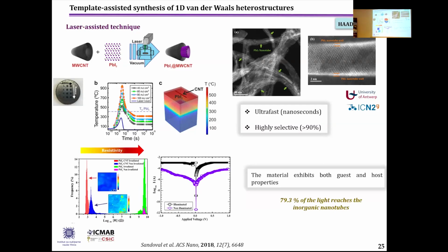And also, we observed in these materials that the material exhibit the properties of both the guest and the host. And one advantage of using carbon nanotubes in these systems when we want to apply this material for electronics, for instance, is that carbon nanotubes are transparent. So in this case, up to almost 80% of the light reached the inorganic nanotubes, and we were able to use this material as transparent hosts, let's say.